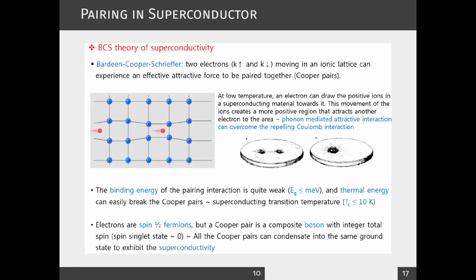So there is this binding energy that's measured in millielectronvolts. It can be in the range of 30 millielectronvolts for high temperature superconductors, and can be 3 millielectronvolts as for niobium or less. Usually these Cooper pairs are singlets, but quite recently they have turned out to be triplets too. So there are certain cases of superconductors that tolerate magnetic field. All right, so that's this theory. We need to spend at least one lecture on BCS theory, and this will be necessary. So we'll see.